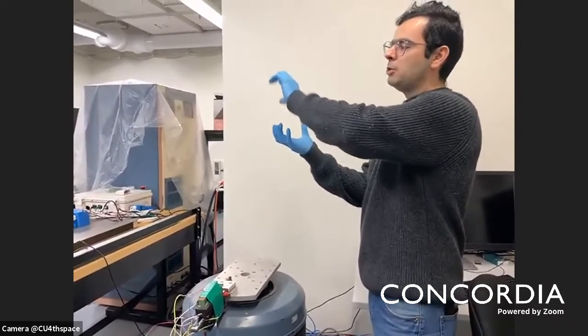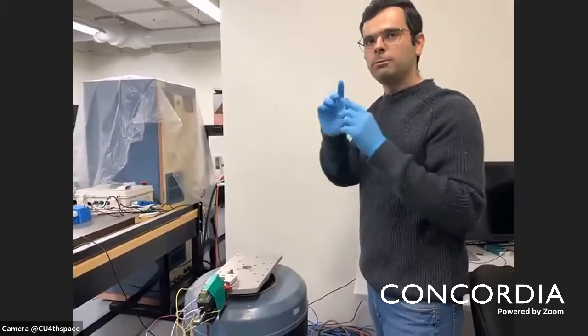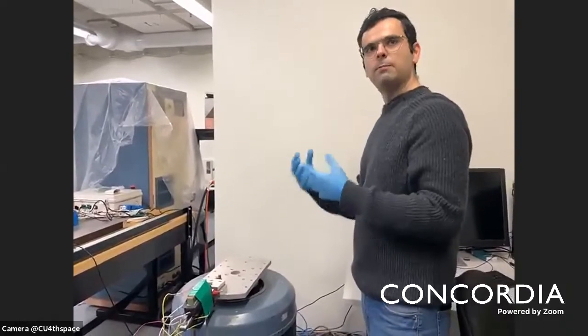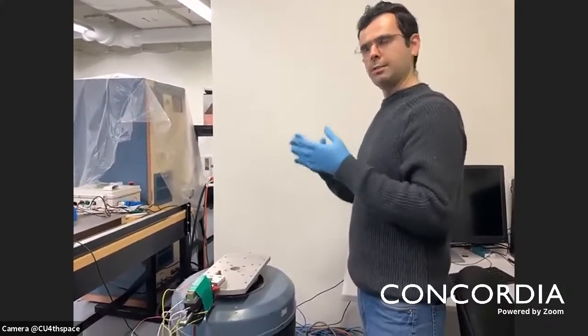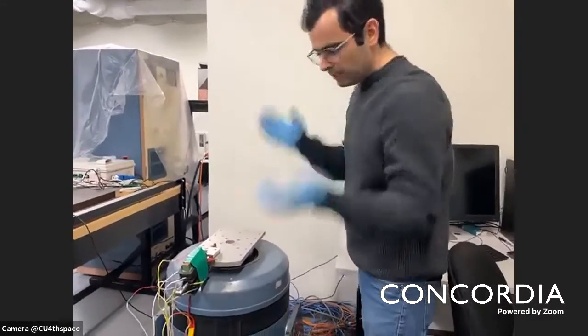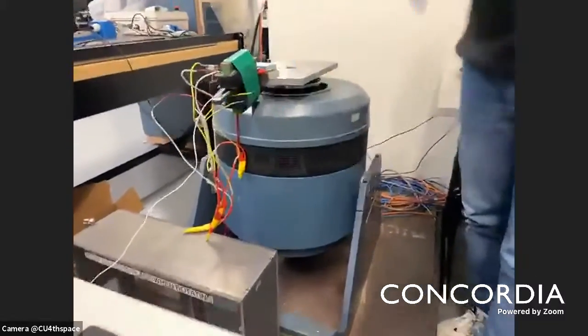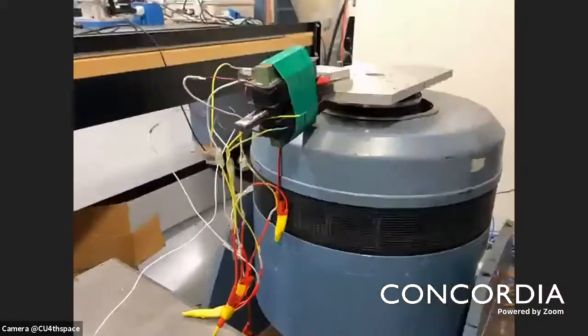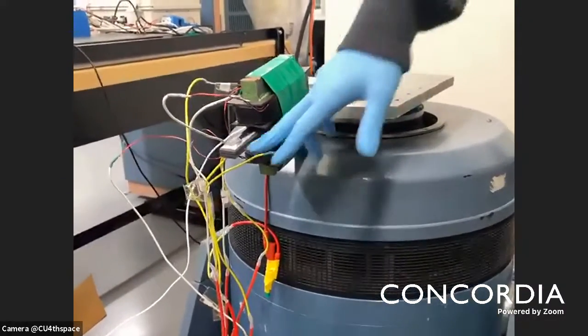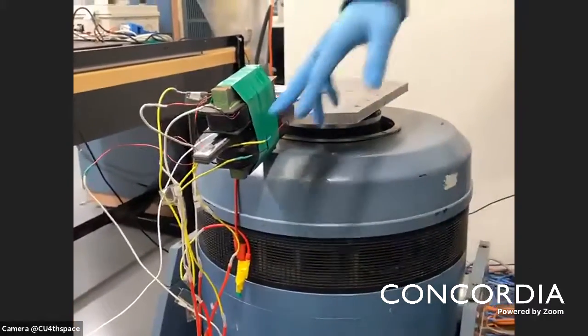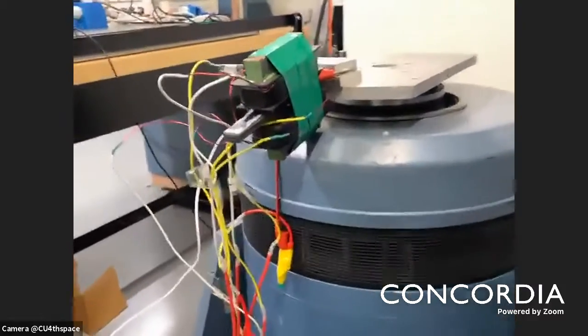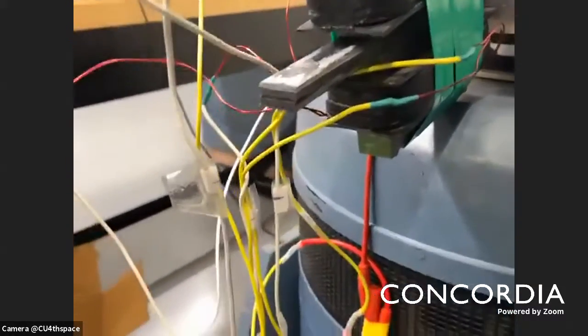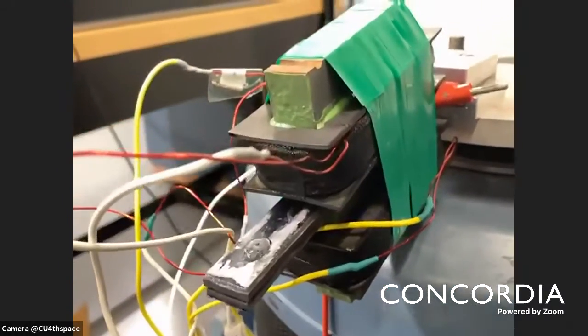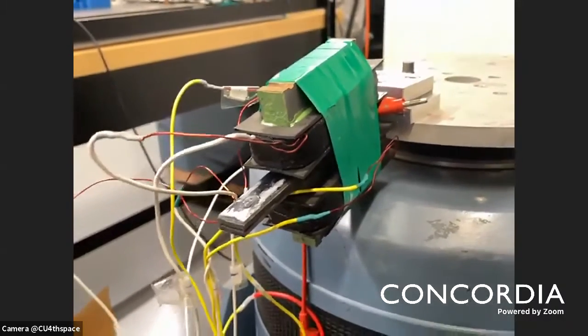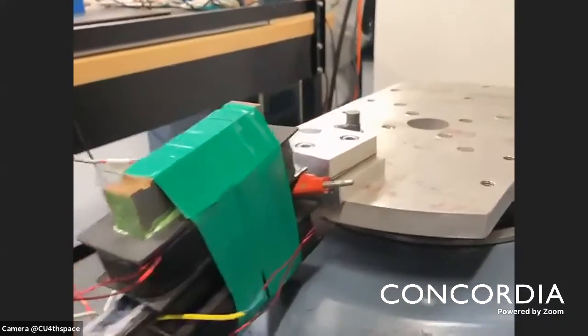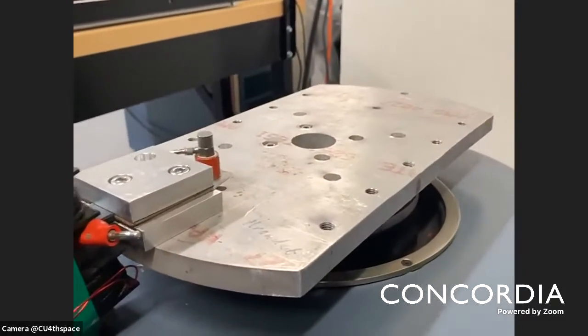If we use a passive spring, it only works for just one frequency, 2 Hz. If the excitation frequency varies, the main system becomes vibrating. You can consider it as a washing machine. But if you put MR elastomer material here, by varying the current into this coil, we vary the magnetic field and could vary the stiffness of the material clamped between these two aluminum sheets. Thereby, we could vary the natural frequency of the absorber mass, and we could reduce the vibration of the main system for a relatively large range of frequency. So these are just characterization desktops that could be opened and controlled.